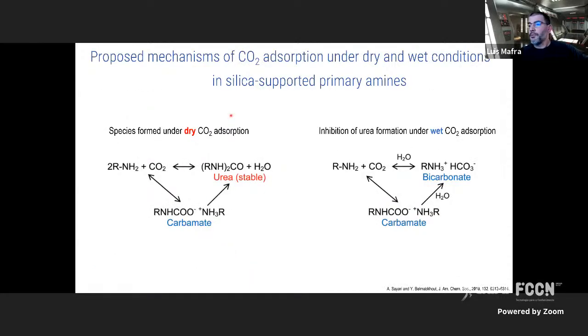I would also like to tell you that various mechanisms for CO2 capture have been proposed, taking inspiration from amine solutions. I show here two routes for some of these mechanisms. One at the left leads to the formation of an ion pair, if you go down this way. And in given conditions, it may also yield urea molecules, urea linkages. Once urea is formed, the system doesn't go back under dry conditions, and deactivation occurs.